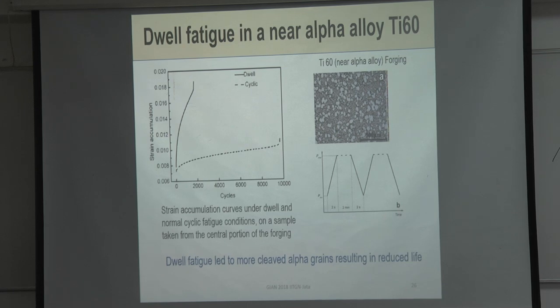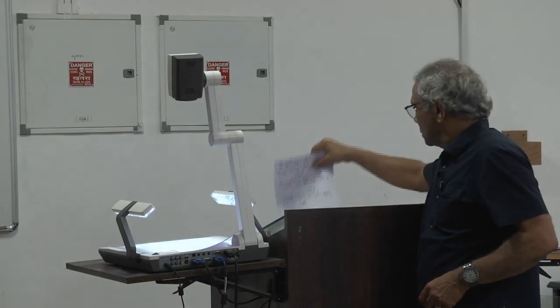The sample was taken from the central portion of the forging. And again, dwell fatigue led to more cleaved alpha grains. Now I want you to be careful that cleaved alpha grains are the same as slip band cracking. Remember, we put up on the sheet all that stuff, all those things.